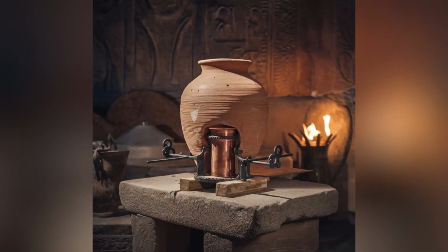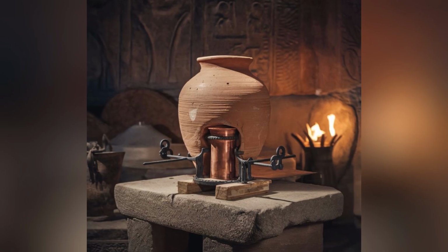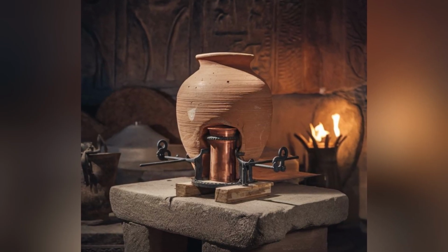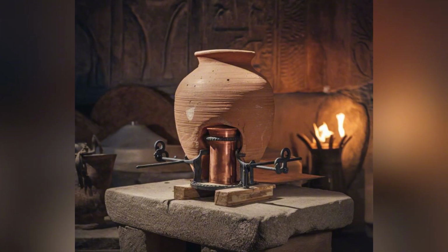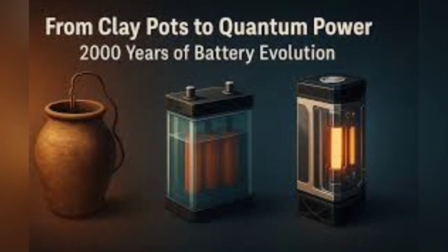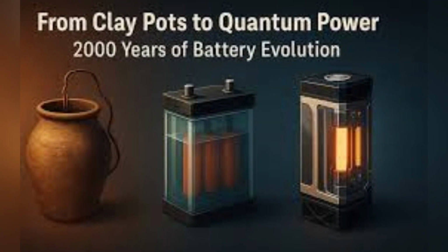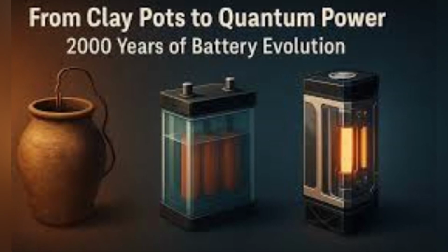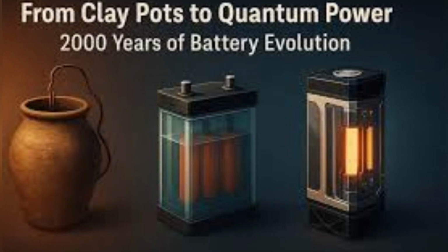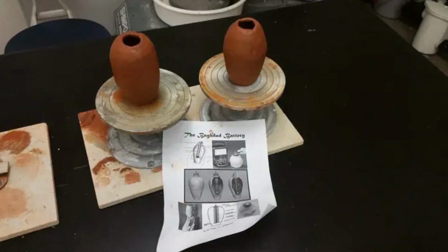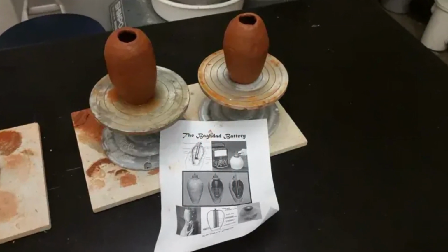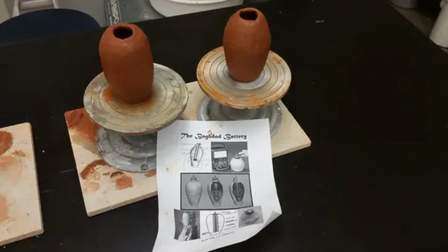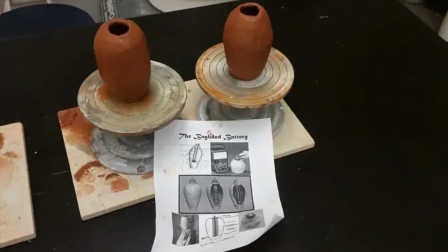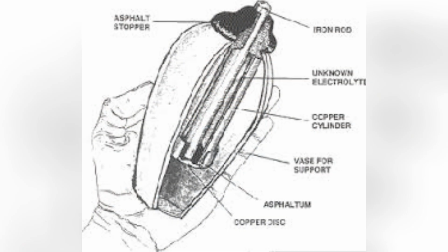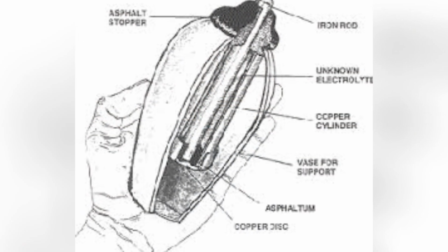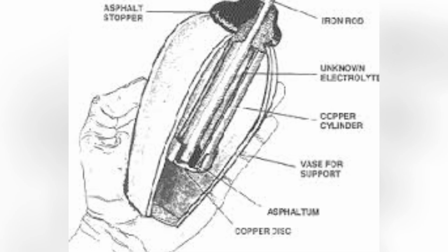The results have shown that the device can produce a variety of chemical effects, including the corrosion of the iron anode, the deposition of metallic copper on the cathode in some electrolyte systems, the production of gas bubbles at both electrodes, and the warming of the electrolyte due to the exothermic nature of the electrochemical reaction. Each of these effects is a potential function of the device, and the identification of the specific effect that the ancient users exploited, if any, requires contextual evidence that is currently unavailable.